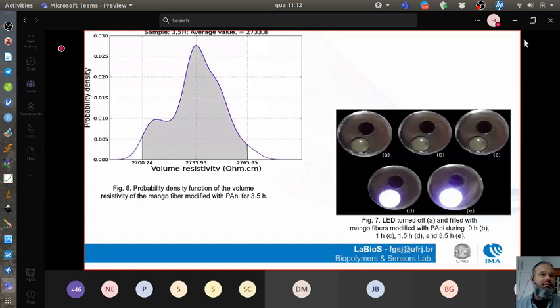Then we studied the volume resistivity of these materials. So in the left corner of this slide, we have the electrical resistivity. For comparison, the electrical resistivity of the mango fibers without the treatment is around 300 mega ohm. After the treatment, for 3.5 hours in the presence of the PANI nanoparticles, the volume resistivity dropped to around 3 kilo ohms centimeter. So the modified material is 110,000 times more conductive than the mango fibers.